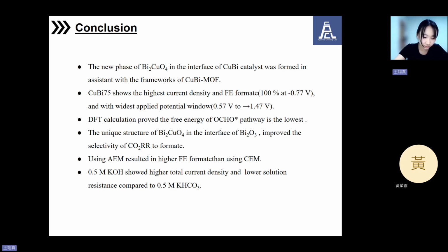As for system optimization, using AEM results in much higher formate efficiency than using a CEM. Lastly, switching the electrolyte from KHCO3 to KOH not only increases the total current density, but also reduces the solution resistance. This result highlights the importance of both catalyst design and electrolyte and membrane configuration in developing higher performance systems for CO2R to formate.